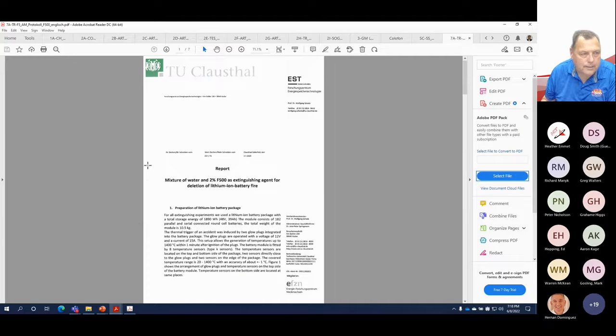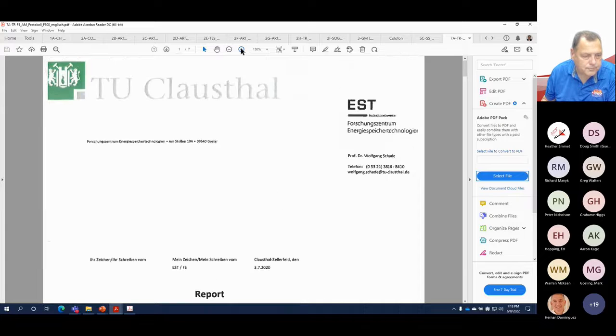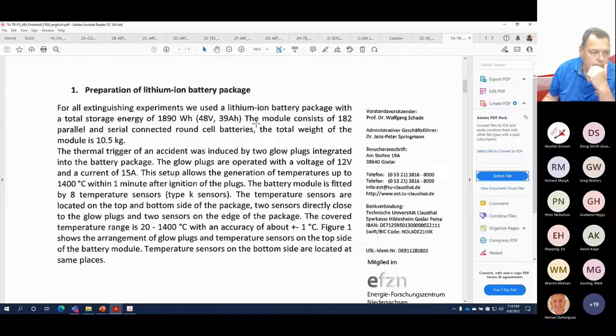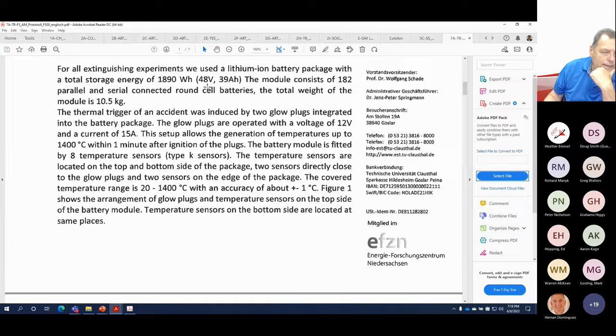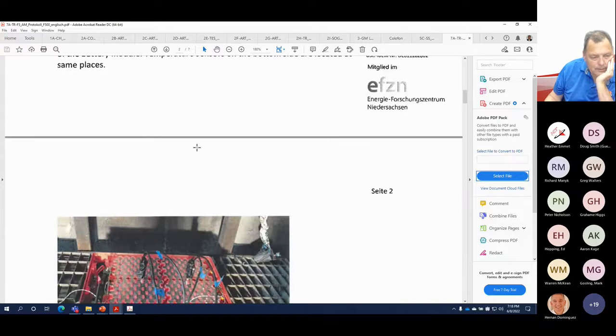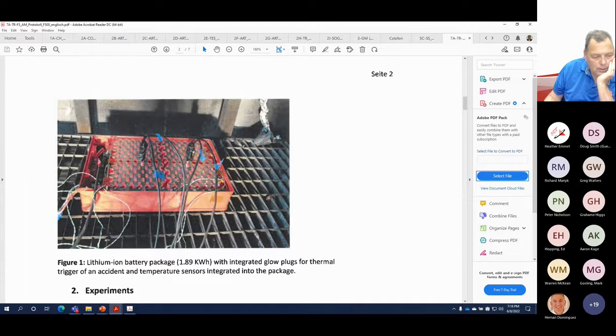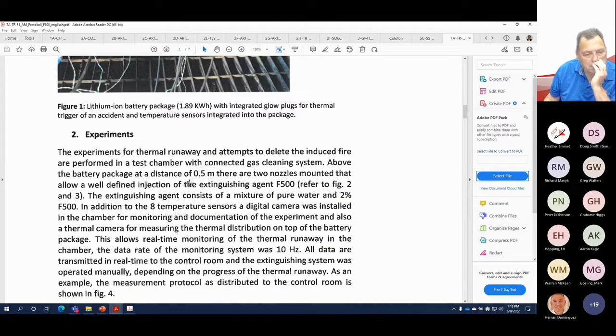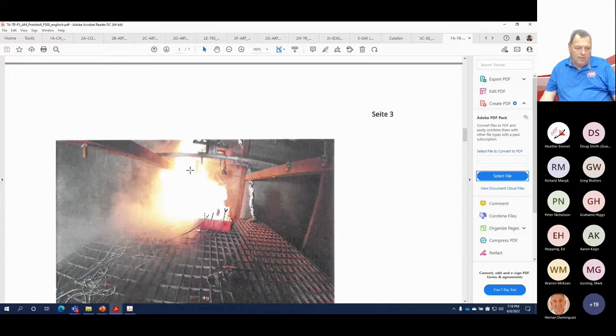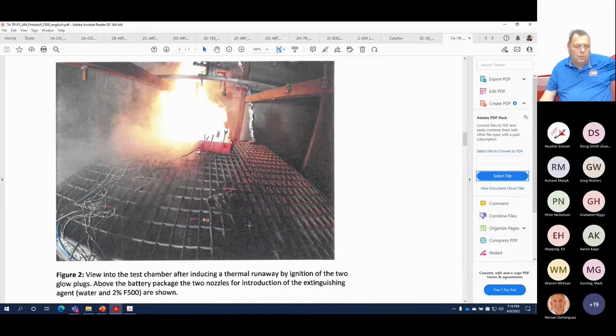One of the tests that we ran, and I think this is a significant test. Here we're taking an 1890, so this is very similar to what we did at Kiwa. The temperature range of the sensors was from 20 to 1400 C, and they actually topped out at 1400 C. So we're not exactly sure whether it was above 1400 C or not, but in this experiment, they put the batteries into thermal runaway, had 8 temperature sensors in place. The agent is being delivered through 2 mist style nozzles at the 2% solution.